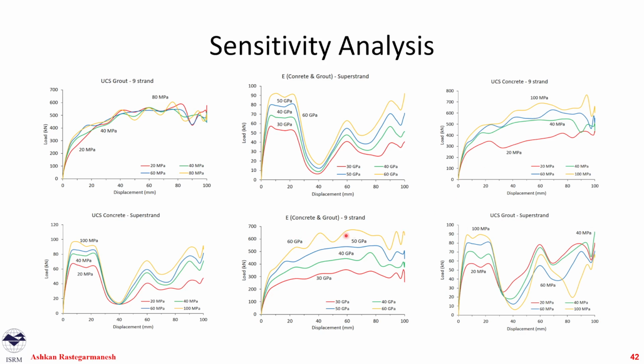But the E, the modulus of elasticity, actually has a higher effect for our 9-strand cables, which are the bolt cables. But for our super strand cables, we see that the change in UCS of the concrete and grout and the modulus of elasticity has a higher effect on both of them.